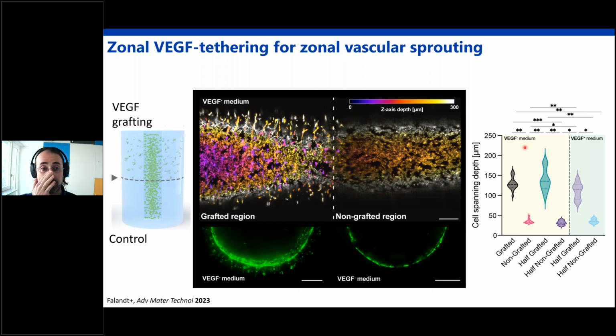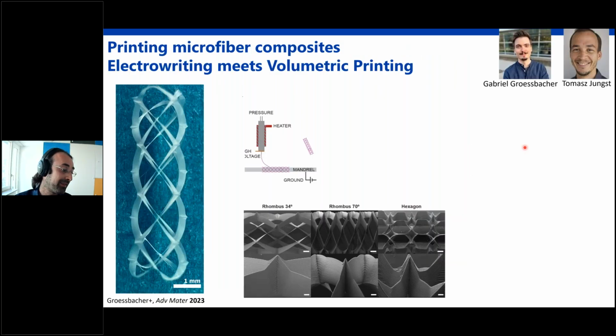And one last thing I wanted to touch upon is that everything I showed you is actually a single material with this chemical modification. But I mentioned at the beginning that one important aspect of tissues is that they are not just monomaterial, but multi-structures. That's a work we started tackling with one of my students, Gabriel, and the team of Tomasz Jungst at Würzburg University, where we create composite materials combining light-based printing and melt electrowriting. Melt electrowriting, for those that are not familiar, in a very simple way is a sort of combination between fused deposition modeling printing and electrospinning. So you can get very thin fibers out of thermoplastic materials, for example PCL, what you see here.